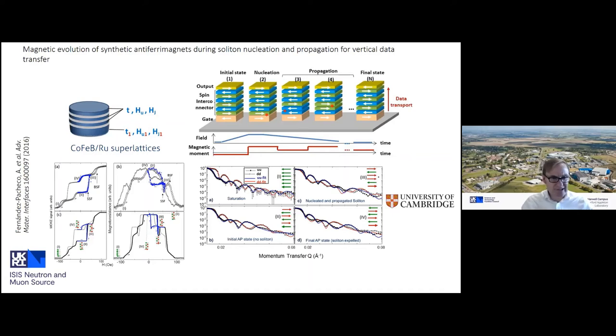If you look at a conventional technique like MOKE, for example, you get these complex patterns where you can sort of indirectly infer what might be going on. But with polarized neutrons in this case and reflectometry, here's some of the data, you can absolutely definitively define what these structures are. So these structures that you see here are cartoons, but they're extracted from the neutron data. So we precisely know what's going on in our little structure. So there's an example of a metallic system on the nanoscale.